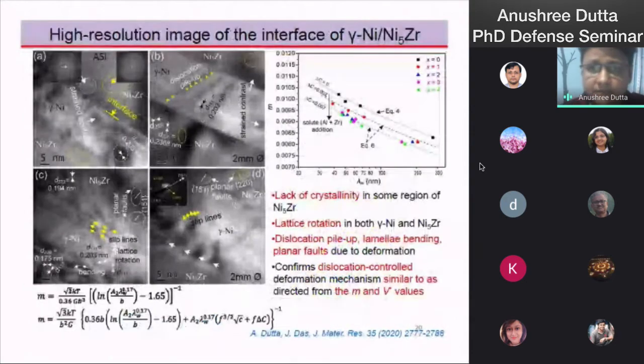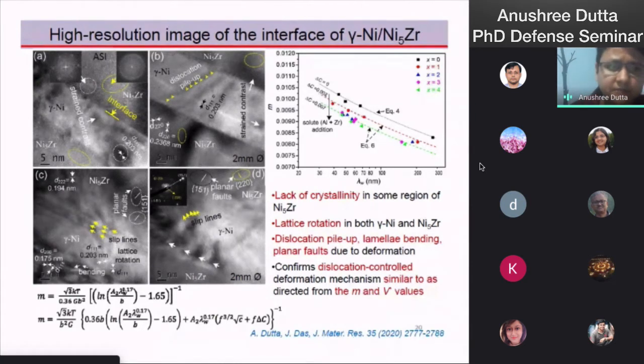The high resolution image of the gamma nickel and Ni5Zr shows lattice rotation of the gamma nickel phase in several regions of the gamma nickel lamellae. In the FFT pattern, it can be observed that the nickel zirconium lattice crystallinity has been destroyed in some portions of the Ni5Zr lamellae, where the FFT pattern shows an amorphous-like structure, whereas in some regions crystallinity is maintained, showing the crystalline pattern. We can see dislocation pile-ups, slip lines and several planar faults after deformation.